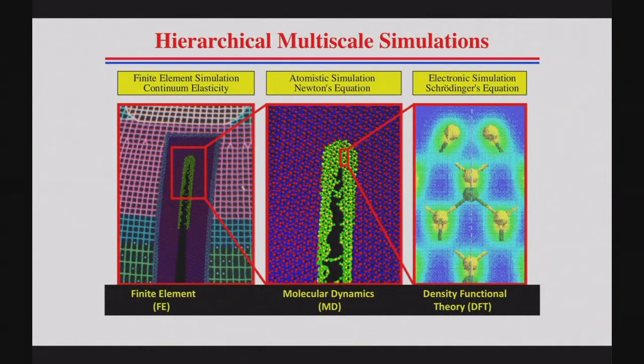And we have developed a scheme where we can embed molecular dynamics in finite element, and in molecular dynamics, we can embed quantum mechanical calculations. And this sort of bridges the landscapes. And we have tested this to make sure that the transitions between these different schemes are seamless.